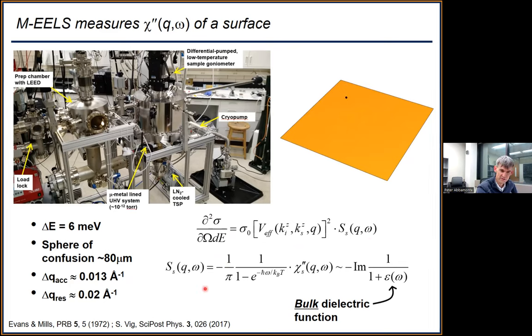And S satisfies what is called the fluctuation dissipation theorem. So this spectrum of fluctuations is proportional to the imaginary part of the Green's function. And that's basically the dynamic charge susceptibility that I showed you earlier, with one difference: it's actually the susceptibility of the surface. And that's an important distinction that's discussed in these papers. I'm going to gloss over that a little bit because it's not going to be that important for what we see, except at the end when we do the sum rule.